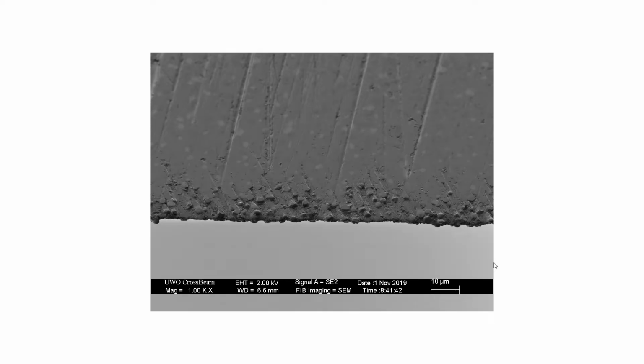Now compare that with the full image here. You can see I cropped the top portion of that picture, which is what we just looked at. The bottom portion was actually micro beveled with a natural Japanese stone, or Japanese water stone, which definitely is not hard enough to abrade the carbides in Maxamet. And you can see just how much of those carbides are sitting out and how jagged the edge is, and just how loosely those carbides are held in the surrounding steel matrix.